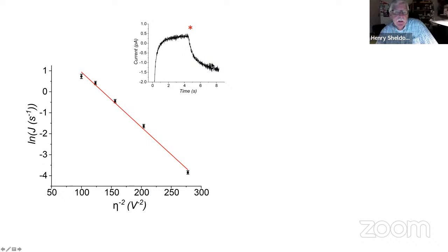The amplification, of course, is the growth, right? The confinement in this experiment is using a tiny electrode, so you only get 1 nucleus. And then the amplification of that signal is the very rapid growth. So you're talking about silver ion diffusion on a 100 nanometer scale. That's just infinitely fast. Okay, so this is growing really fast.